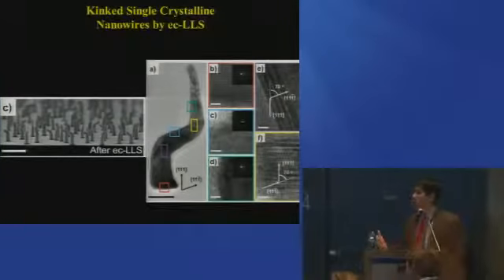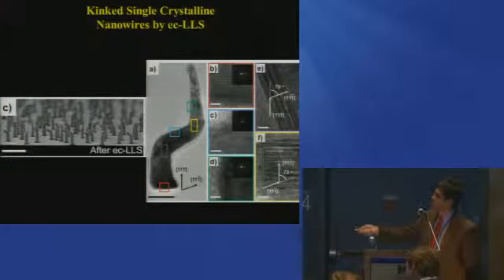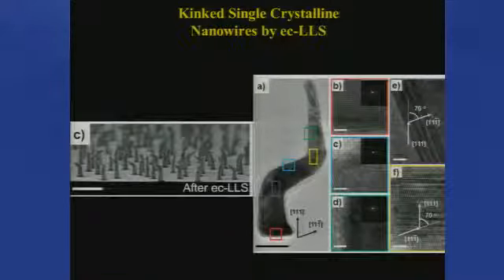And we've been able to sort of figure out that in this picture, there's a lot of little clues that are being told to us, and there's still some mysteries that are still here. We know that these wires, when we try to grow them long enough, they start to bend over, or they kink at some point. That kink, if you take a look at one of these nanowires with, again, high-resolution electron microscopy, it turns out these kinks don't mean that your crystal stops growing. It just means this crystal has sort of changed its growth direction, but this is still one continuous single crystal.